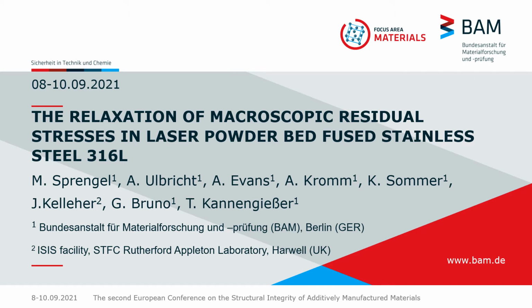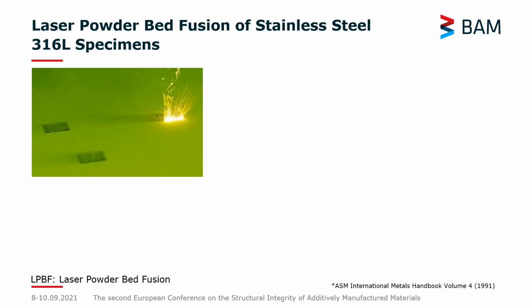Today I will talk about the relaxation of macroscopic residual stresses in laser powder bed fused stainless steel 316L. The laser powder bed fusion process is an additive manufacturing process where we use a laser to locally melt up metallic powder and build parts in a layer-by-layer fashion.